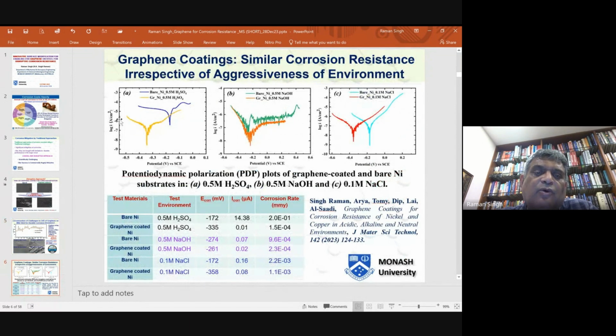Also, when you have graphene coating on nickel, irrespective of the aggressiveness of the environment, the corrosion resistance is the same. That's what this slide shows. The intercept of these two arms gives me corrosion resistance, this point. And this point is the same in every plot that I'm showing you. That shows that corrosion resistance of graphene coated nickel is the same irrespective of whether I'm testing in highly aggressive sulfuric acid, or aggressive sodium hydroxide alkaline solution, or neutral solution.